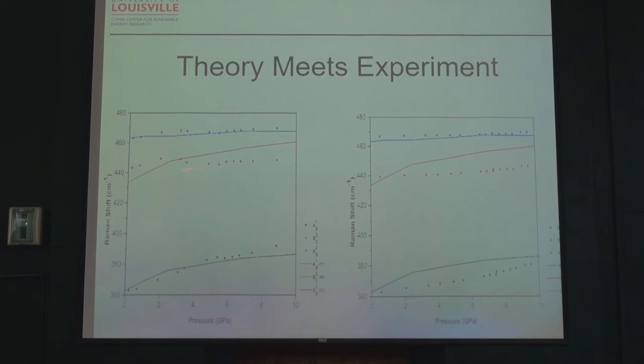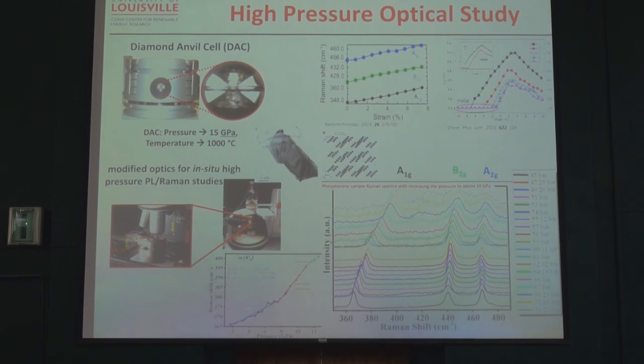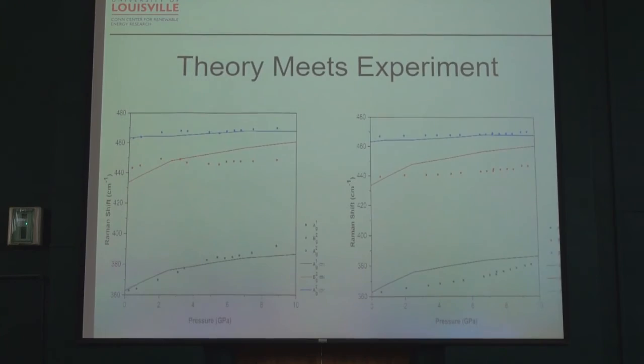So this is the experimental result for two different samples. We have one sample taken from here, which is more like a monolayer. Then another taken from here, that has maybe 10, 15 monolayers. So this is the experiment. This one is from the monolayer sample, so that's this result. Then we had somewhat similar results for this sample that has many layers.